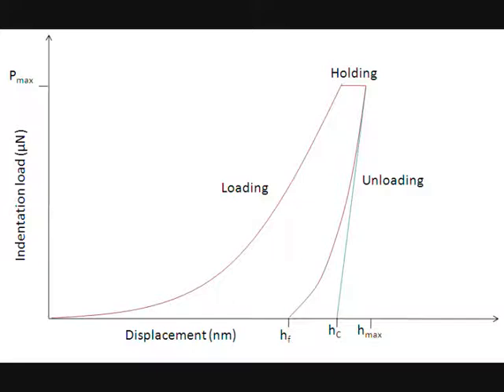This is the typical load versus displacement curve. During the loading phase, load increases with time, and after attaining the maximum load, holding is done, and after holding, unloading is done. We can measure the reduced modulus by drawing a tangent on the initial portion of the unloading curve.